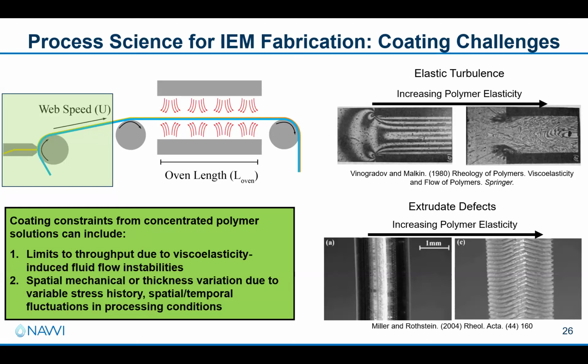So essentially, what happens as you increase polymer elasticity is that you can get transitions to elastic turbulence, where stress building up and developing within the flowing extrudate or flowing coating can essentially dissipate in the form of turbulent flow. This tends to be extremely undesired in coating and extrusion processes because it ultimately leads to non-uniform coatings, or in an extruded material, it'll lead to stress development that, when you start to try and handle the material, will cause the material to deform in ways that you wouldn't expect it to.